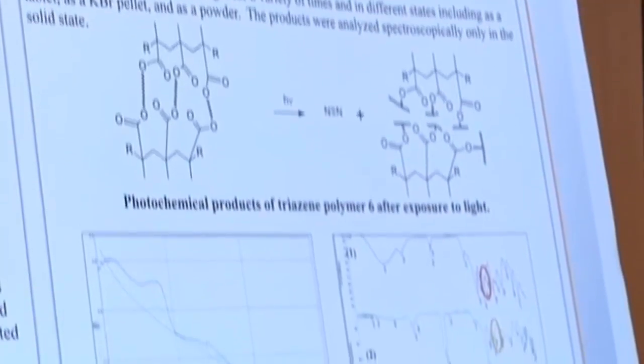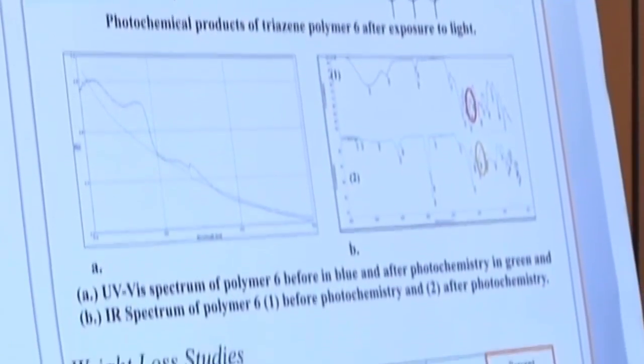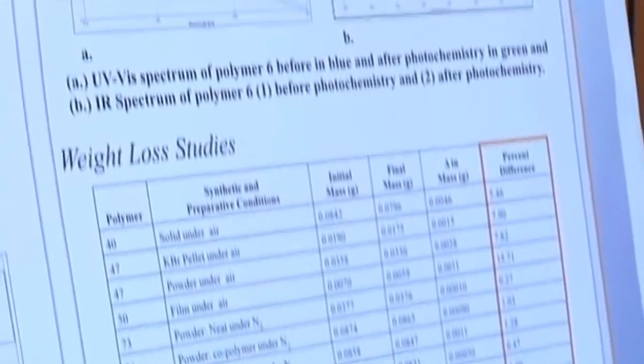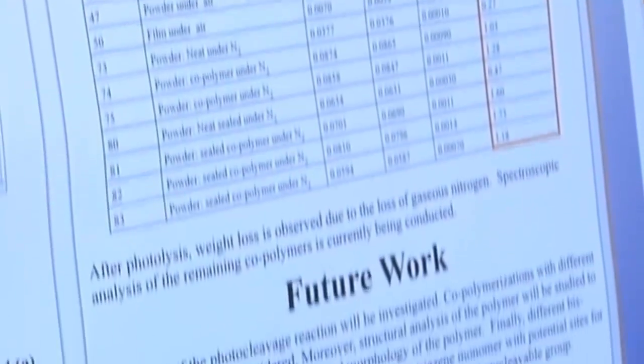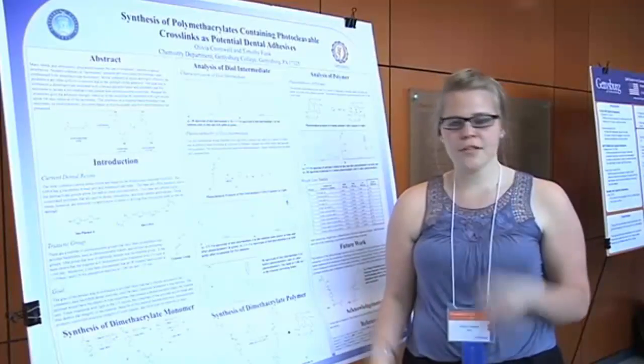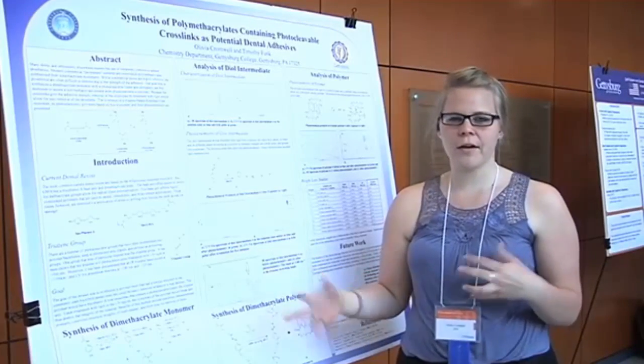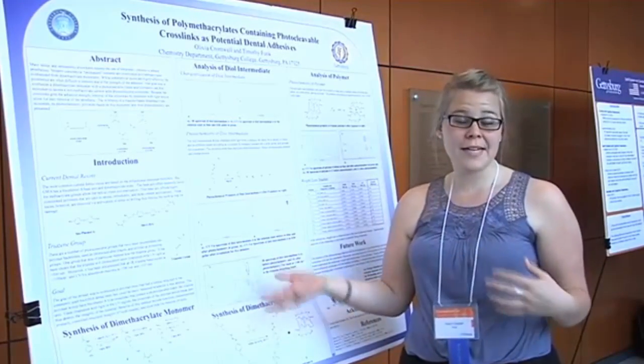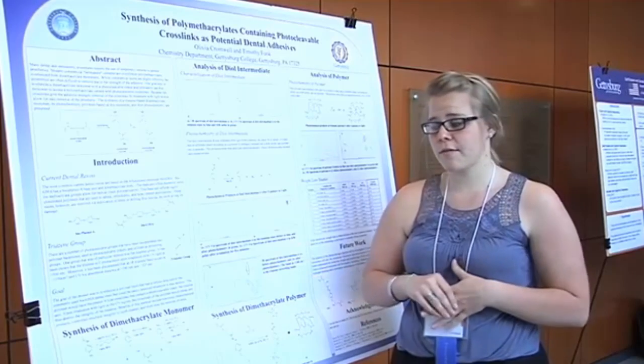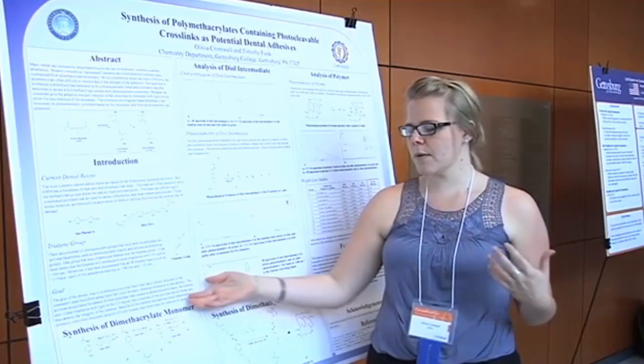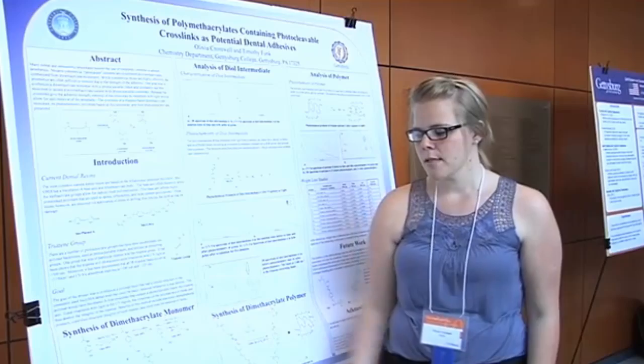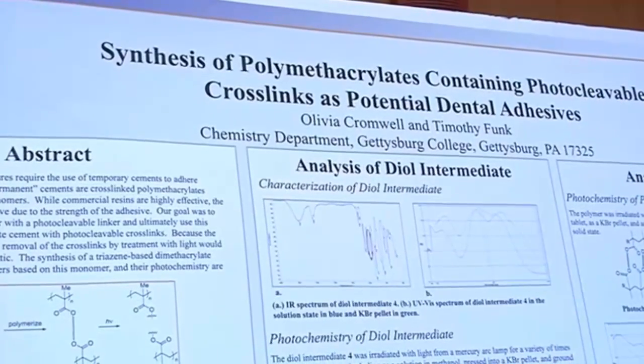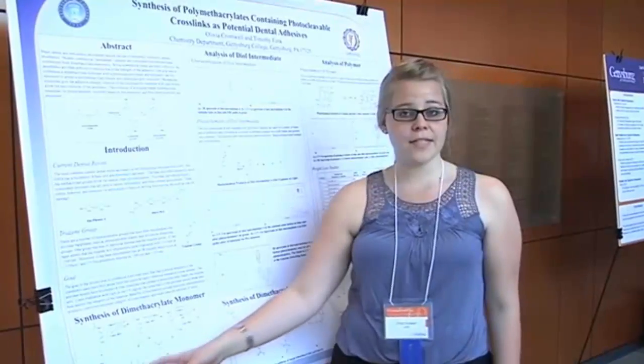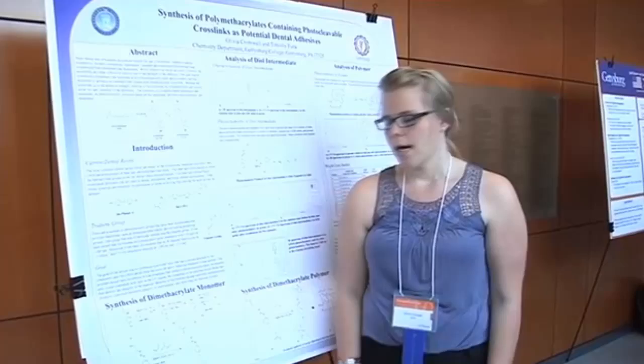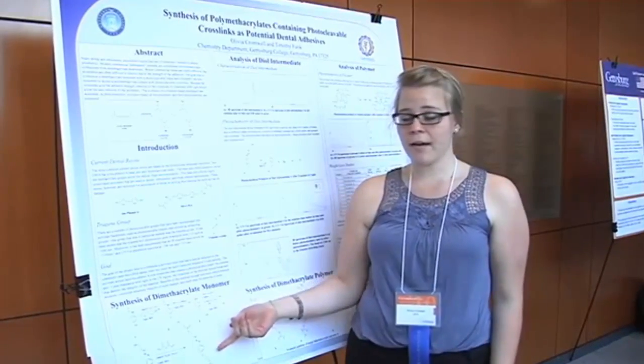What we were interested in doing is developing a polymer that was similar to the structure of bis-GMA, but had the photocleavable group worked into it. And so we looked at the triazene group. The triazene group has been used in photolithography and other areas as a photocleavable protecting group, so we knew that it could be used for photocleavage. So we worked through the synthesis of our monomer. We studied the synthesis and characteristics of the diol intermediate here because it's more stable than the dimethacrylate.